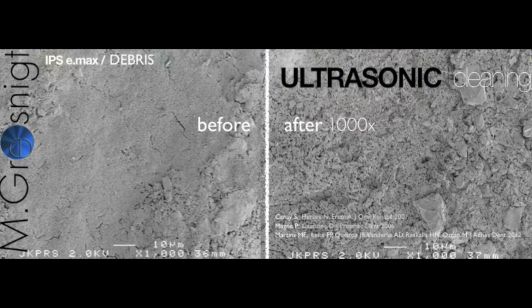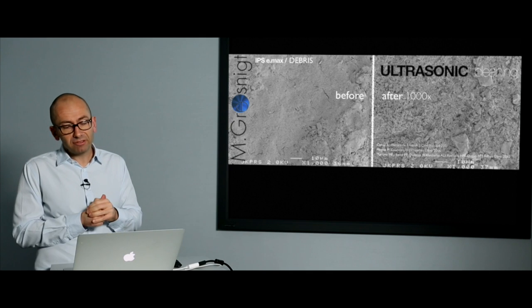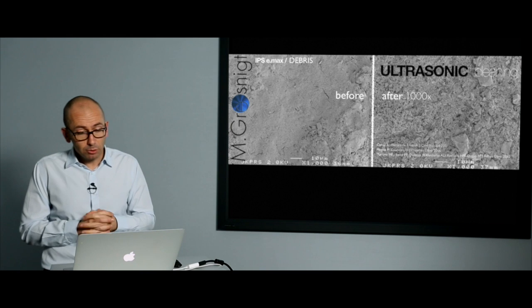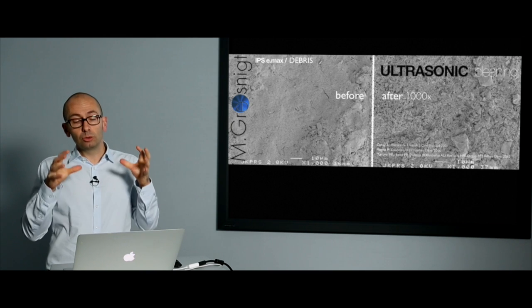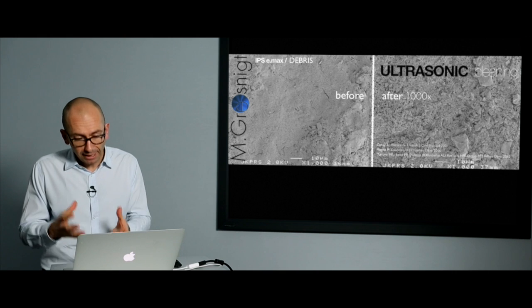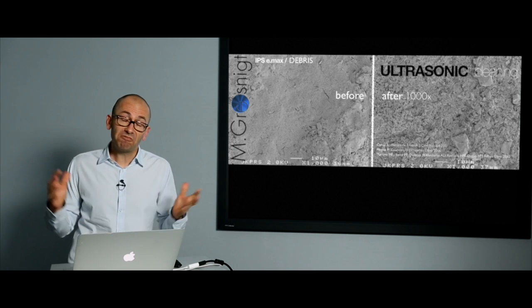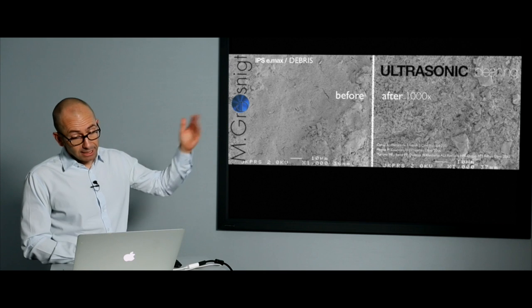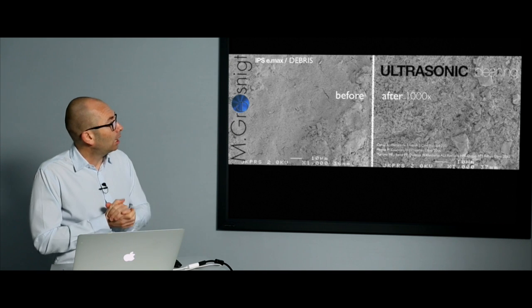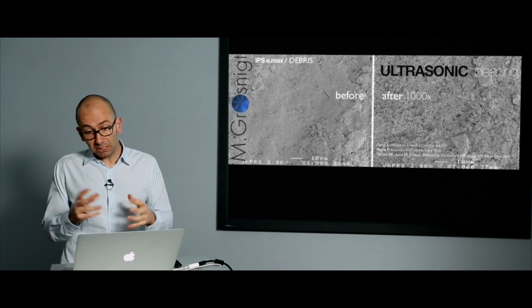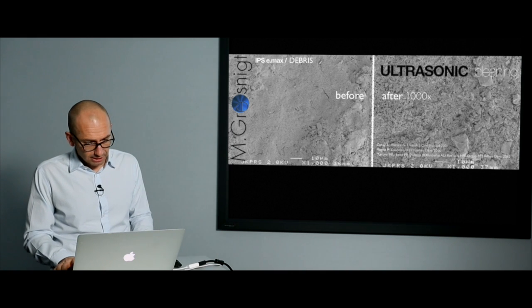After etching, this is what you will get on SEM picture. On the left, you have that surface with a lot of debris on it. And we have to get rid of those debris because we want the bonding to go inside those little irregularities that we've created. And to get rid of those debris, the best solution is to put the veneers in an ultrasonic bath with alcohol during 5 to 15 minutes. And this is what you will get on the right afterwards. And it looks pretty nicer and a little bit more proper, ready to bond, I would say.